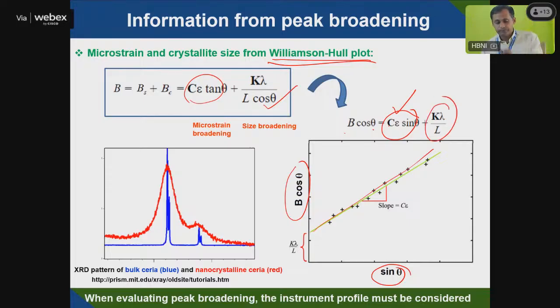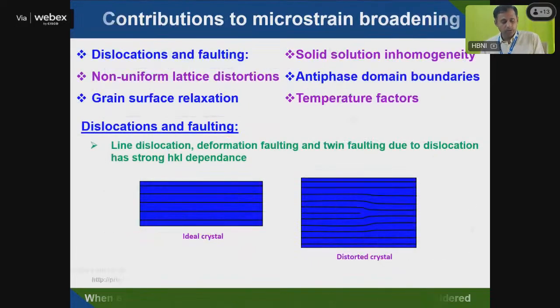Okay, so you can see here, this is a bulk ceria and a nanocrystalline ceria. Bulk ceria is where a sharp line is observed. In case of nano, line broadening occurs. So this type of information you can get from this XRD. In addition, other dislocation and stacking fault information: all those you can see here, the lattice plane is going straight. But here you can see the lattice plane is bent, and one lattice plane is going and comes closed here. So this is nothing but dislocation.